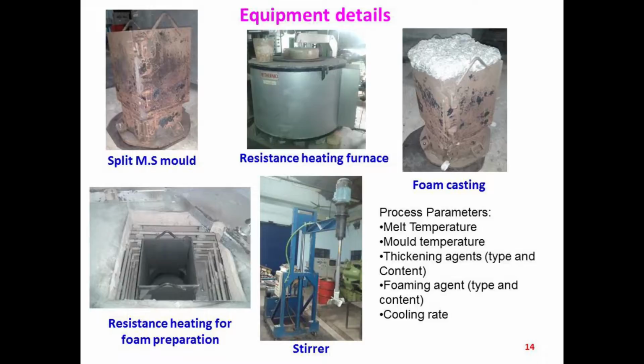And now we have established a semi-automatic system. This is the furnace where we can put around 6 to 8 crucibles which are preheated at a particular temperature. Then we have another furnace where we can melt these materials, and another furnace where we can make the foam. We take the crucible from here to that furnace. There also we control the temperature, and melt is taken from this furnace to the foaming furnace. This is the stirrer which can be put on this, and it is hydraulically operated. It can go up and down. We also have one crane. That crane is used for shifting all the crucibles, and also the crucible after foaming. So it is semi-automatically developed, and it can be developed with much more automation for increasing the foam production.